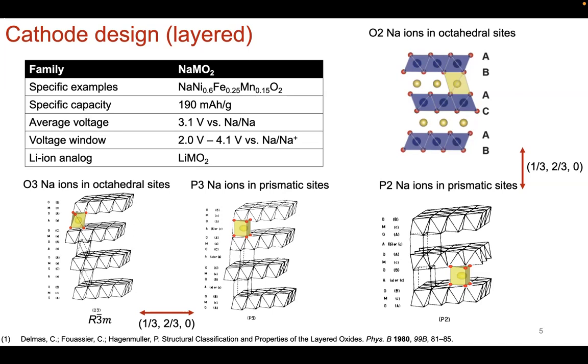Here we'll focus on the NaMO2 type structure, specifically replacing manganese with nickel and iron. Capacity wise, it's somewhat competitive at 190 milliamp hour per gram of active material. The average voltage relative to sodium plus is 3.1. So that's pretty competitive, pretty high. Although the voltage window is really large because that's just the average.